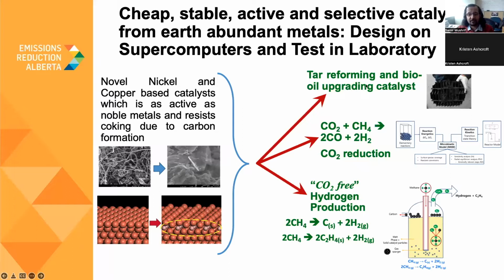One is tar reforming and bio-oil upgrading, where one of the major challenges with the catalyst is that they are not stable because of carbon formation, and we can modify those catalysts to avoid carbon formation. An additional challenge in bio-oil, which is very corrosive, is that you need to selectively remove oxygen without breaking the carbon-carbon bonds in bio-oil. And we are developing those catalysts that can selectively do the job without excessive requirement of hydrogen.